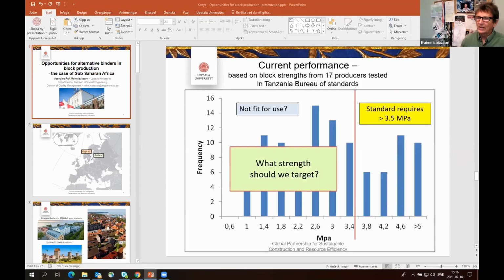When going to the Tanzania Bureau of Standards to get some idea, and these are the better blocks which have been taken there for testing, which go to governmental projects or schools, still they come out with a variation which goes from 1 to more than 5 megapascals. And the standard basically says 3.5 as a minimum for the individual block, but 4 megapascals as an aggregated average for 5 blocks. So basically, most of these are substandard.